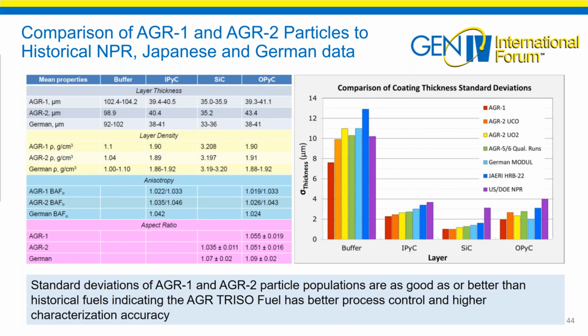They need to have their pebbles to be buoyant. Now, you don't just go out and make your own particles and then say, oh, well, we think we're like AGR. No. We worked with them during a GAIN meeting and said, look, you can actually, if you know how to make a pebble, like for instance, if they work with X Energy, if you know how to make a pebble, then you can make an unfueled region in the center, like a little ball instead of the tennis ball, let's say the outer side, you can make a little ping pong ball of unfueled, just matrix, and then a fueled region with a packing fraction and the enrichment that you want, and that rind, the unfueled region, and get a buoyant particle. And I did first calculations that it's going to be about an inch, and then they went back and did their physics. Oh, wow, yeah, you could do it.